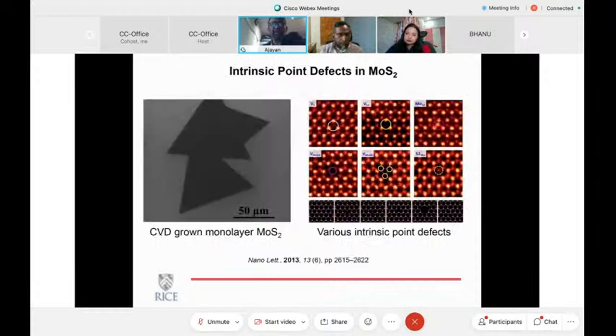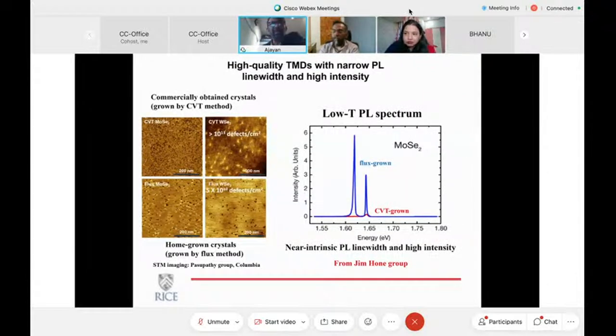There are again other defects in these systems, point defects. I don't have time to go into details, but if someone is interested, this is a good reference to go to. People have documented various types of defects in these systems, particularly the CVD grown ones. And it's very clear that defects have an impact. In fact, this is not from our group, it is Jim Hone's group from Columbia, clearly showing that if you change the density of defects intentionally, your electronic properties change. The low temperature PL spectrum.